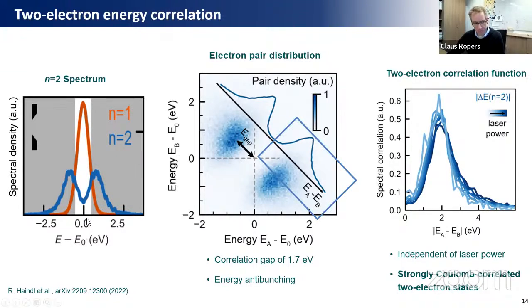So what this means is essentially, for example, we could place an energy dispersing element in the beam path and then select only electrons which are more or less residing near this mean energy. And in this case, you could strongly suppress the 2 electron events because 1 electron has higher, 1 electron has lower energy, and only the 1 electron events can pass. What this would do is essentially produce a sub-Poissonian distribution, so eliminate shot noise from the electron emission process, which could be useful for a number of applications in imaging and lithography, for example.